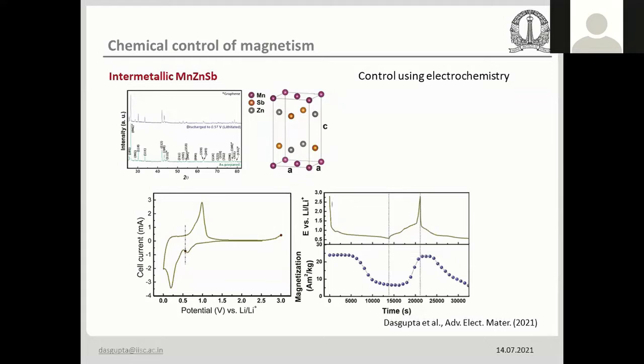This is again an in situ measurement. So you can see on the right hand plot, bottom plot, that we are doing this electrochemistry, which is this dark yellow line. Okay, so this is the discharge charge cycle, and we are measuring magnetization in situ, simultaneously, and those are given with these blue round symbols. You can see that the magnetization is going from 25 emu per gram, or ampere meter square per kg, down to 5. So it's an 80% change in magnetization even for an intermetallic system.